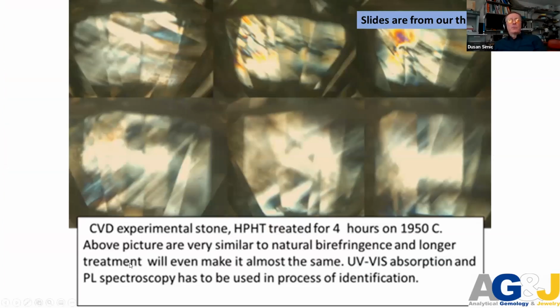But if you treat these stones, for example, for 4 hours at 1950 Celsius, this cross-polarized picture will start to be different. Not any longer so simple, but still, because it is a three-dimensional effect, it is much more clear if you have this in a microscope. When you are rotating a stone, you will still see these defect planes in the 111 plane. But right now it looks like it could be a natural stone like this, but it is not.